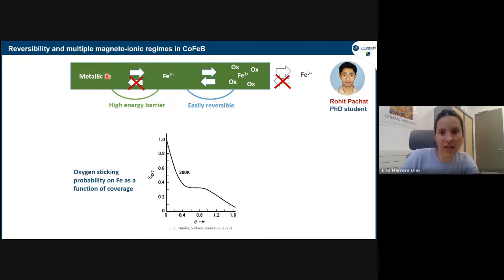And then if we start adding oxygen, we're going to oxidize this iron. So it's going to go from metallic iron to Fe2+. That is a proper electrochemical reaction, a proper exchange of electrons in the system. So this probably has a relatively large energy barrier to go forward and back. However, if we keep adding oxygen, we might have a regime where we have Fe2+ surrounded by more oxygen species, but not quite yet in an Fe3+ state.